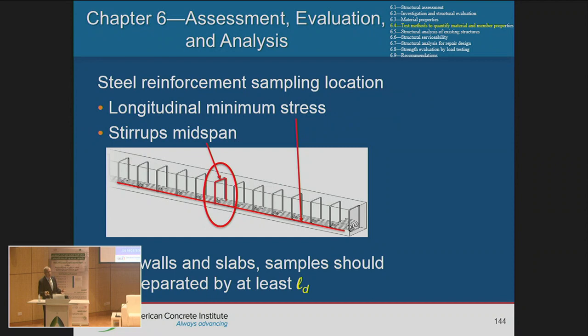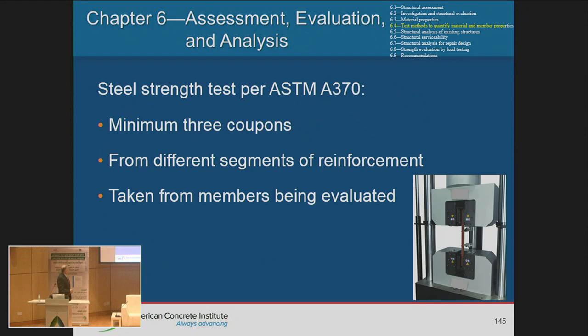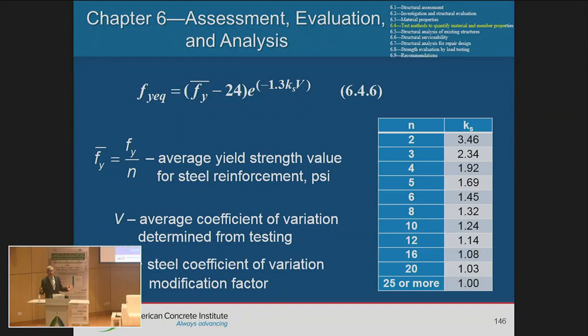And if you have walls or slabs, if you have 2 bars or 3 bars next to each other, when you take the samples, have a difference of about the development length. So you take a minimum of 3 samples from different segments and from the members being evaluated. Again, for steel, we also have an equation, the same thing, Fy bar, that is your average from the samples that you've tested, and that would be your equivalent yield strength from that equation. I will not go into it, but again, if you use a very high number of samples, your equivalent yield strength would be about 85%.